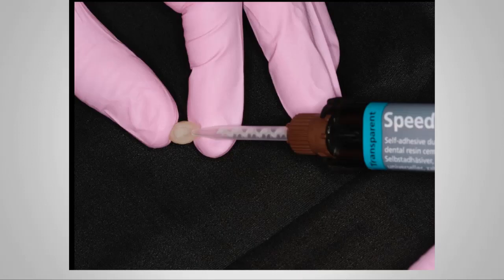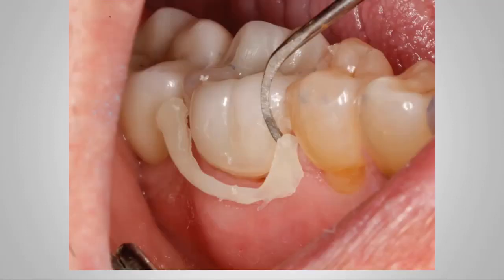This is the SpeedCEM Plus. So it's a dual barrel syringe, and this is a squirt and go. So remember, the adhesive is already in the cement. So we're going to squirt it into the crown, and then we're going to seat it, and then we're going to tack cure. You can tack it just for a couple seconds on the buccal and lingual. The SpeedCEM Plus gets to a really nice gel phase, where it cleans up very nicely and very easily. It comes off in big chunks. You go ahead, still stabilize the top of the crown, floss in between, pull out any excess cement, and then do your final cure, and you can adjust occlusion immediately. Really nice, easy way to deliver your zirconia.